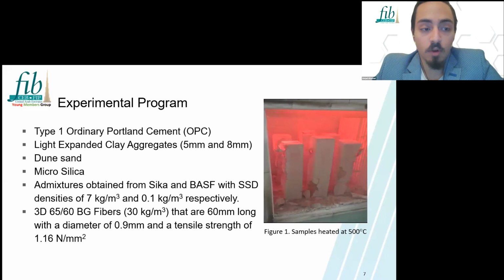Moreover, in the experimental program, as you can see on the screen, these are the materials we use. Most notable are the 5 mm and 8 mm lightweight expanded aggregates and the micro silica, plus the 3D fibers. The 3D fibers are very important in the study. They have a 60 mm length and a diameter of 0.9 mm with a tensile strength, as you can see, of 1.16 Newton per millimeter square.